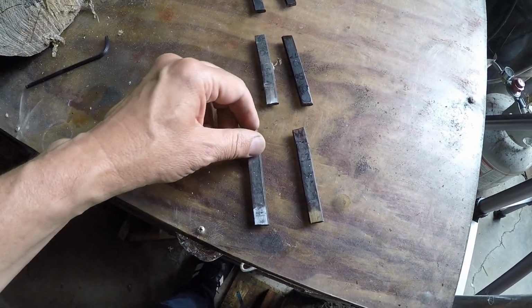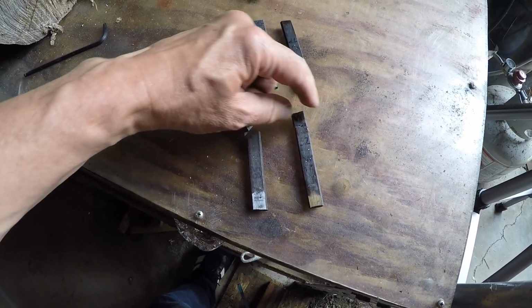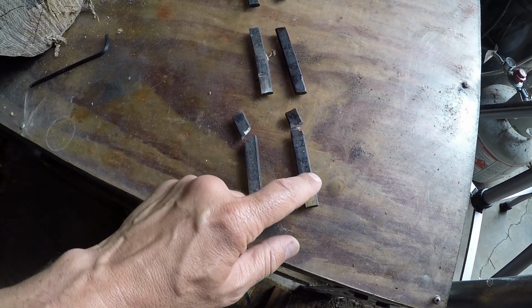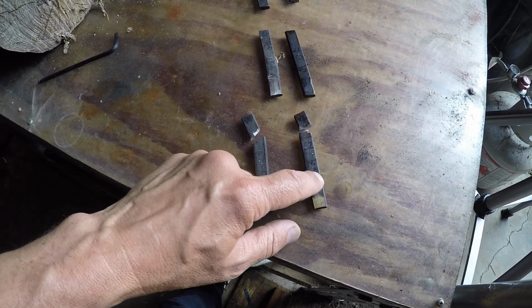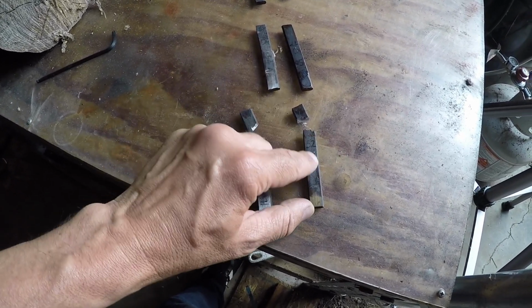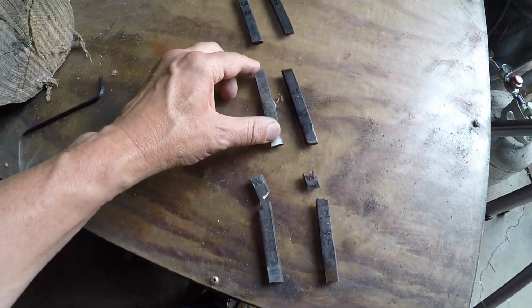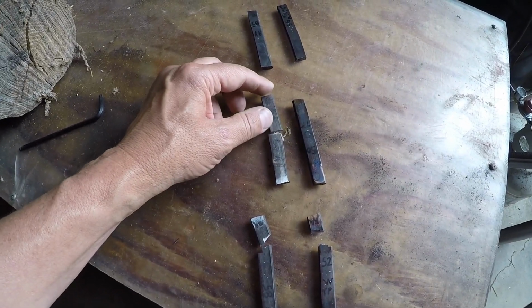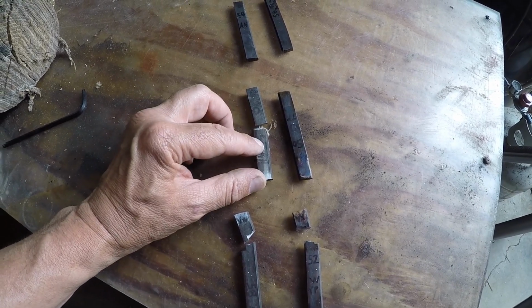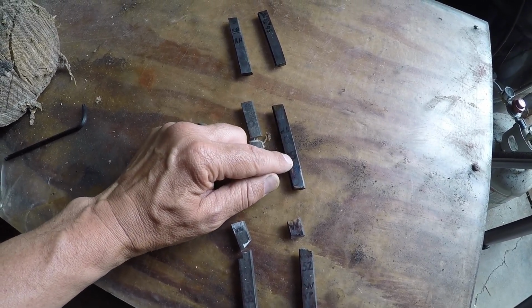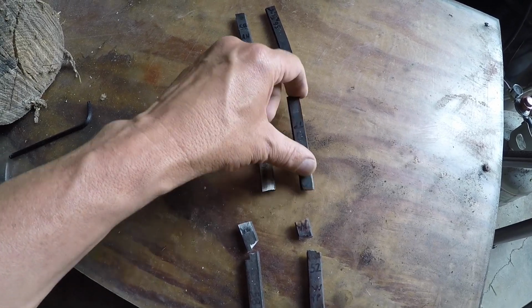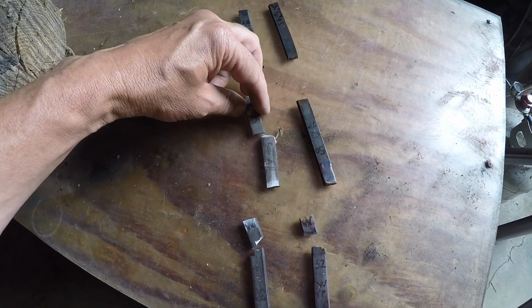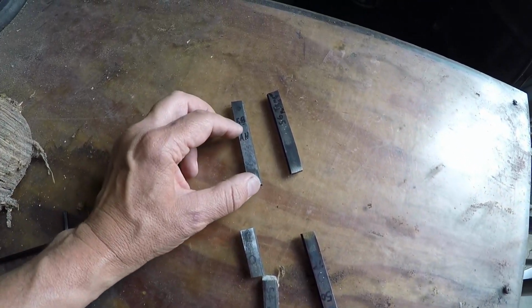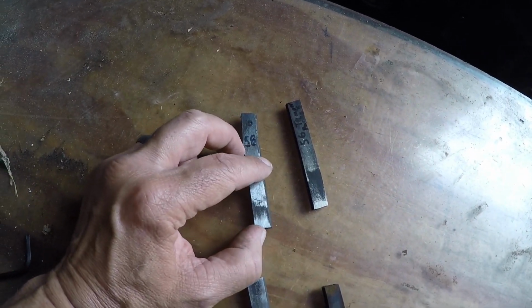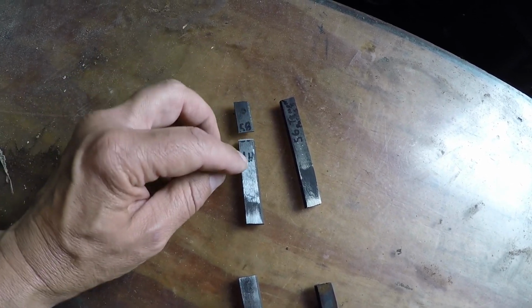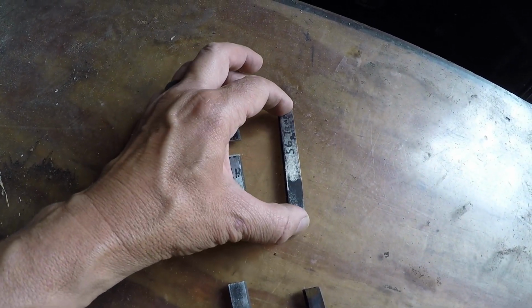So pretty rudimentary testing here. But like I say, both of our waters, this is 58 Rockwell, this is 52, as quenched and tempered, both shattered. We had our oil, which was canola. Canola, this was 54 as quenched, this was 50, tempered 3 times. This one is not broken. This one was broken. And then we had our Parks 50, which again is our preferred quenching medium. There's a 58 as hardened and 56 tempered.